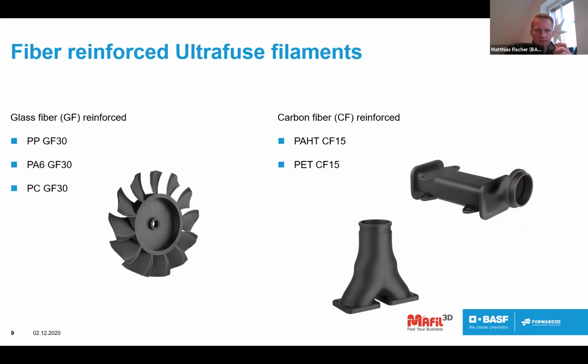So concerning our products, we have at the moment 5 reinforced products in the portfolio. These are 3 glass fiber reinforced filaments. One of them is a PP, polypropylene reinforced with 30% glass fibers. Maybe some of you already got the information this year that we took over the business from Owens Corning, which means we now also have filaments like the PA GF30 and the polycarbonate GF30 in our portfolio, which have really nice performance with regard to stiffness due to this high amount of glass fibers. You can see here a fan on the left side, which was printed with the PP GF30, which can be used, for example, in the automotive industry.